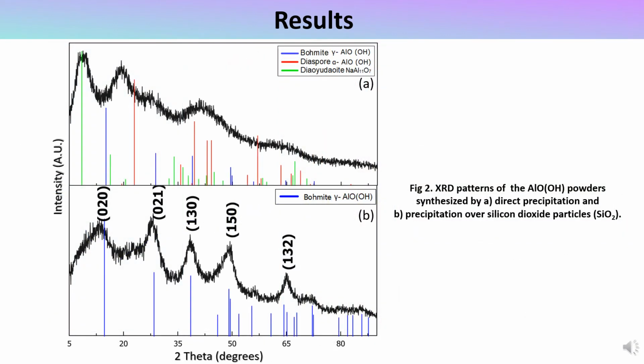In figure 2, we observe the diffraction patterns, the letter A corresponding to the powder obtained by direct precipitation. We observe the presence of planes coming from different phases. The blue color belongs to signals of the gamma phase, boehmite. The red color corresponds to planes of the alpha phase, diaspore. Finally, the green color are characteristic planes for a sodium aluminum oxide. The different phases tell us about a low purity in the powder obtained.